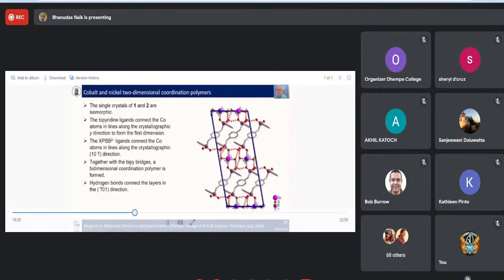You can see the phosphonate ligand forming this bridge here. And also we have hydrogen bonding here, which builds up the 3rd dimension. So you have the 1 minus 1 direction and 1 0 1 directions, which are different. So you have 1 in this angle here, which is a coordination polymer, and this is a hydrogen bonding between the layers.